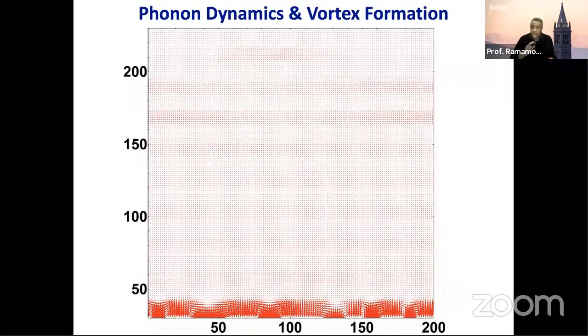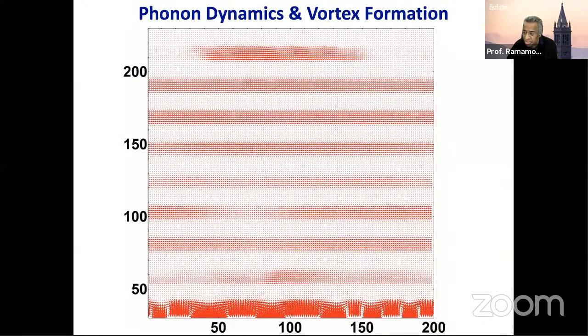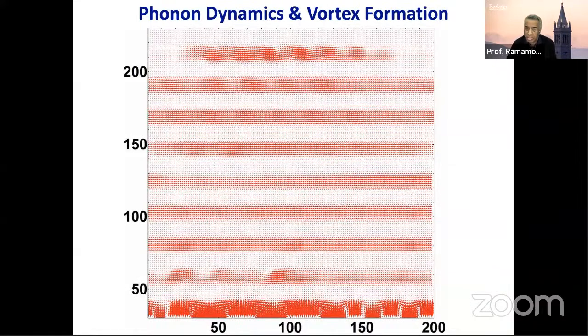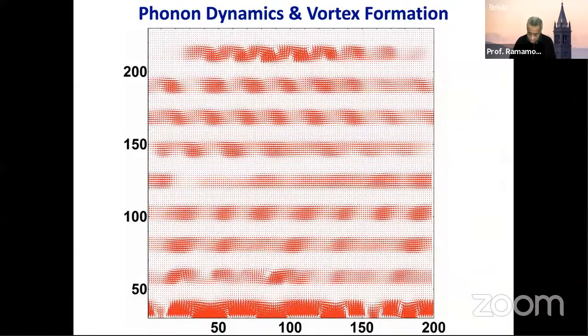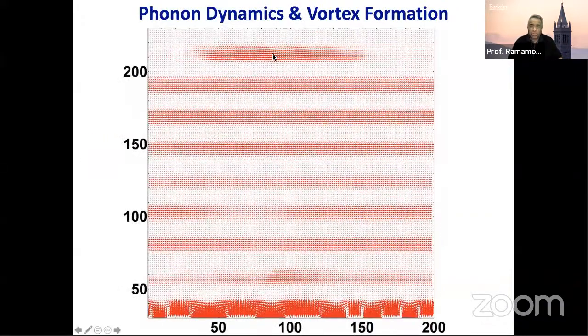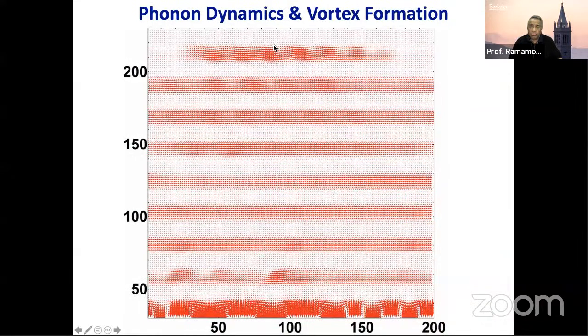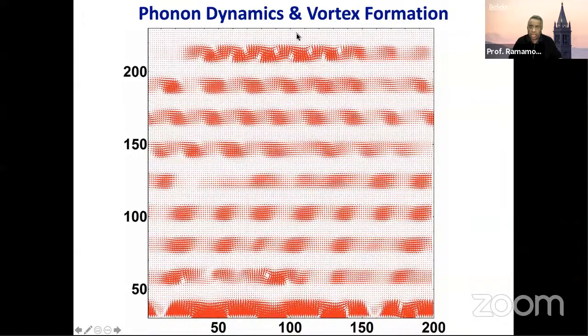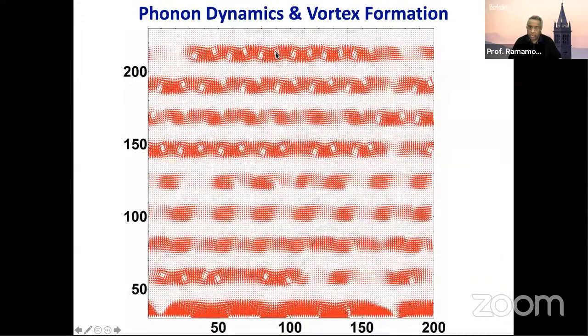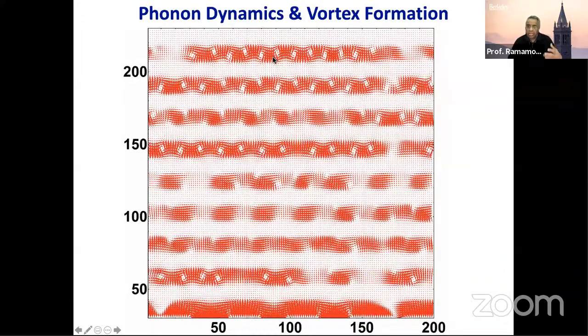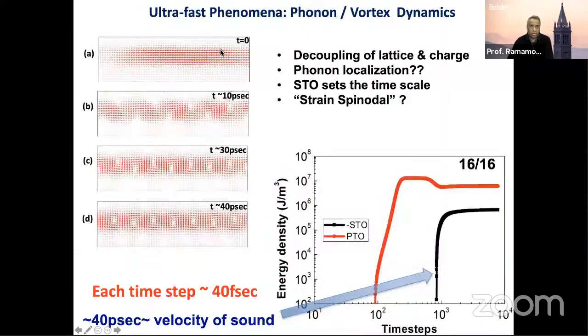So now I'm going to show you the last piece on these vortices, and then we will go to the sister phase. Now, if you look at this picture, what I'm showing you now is time-resolved calculations of how the vortices nucleate. If you pay attention very carefully, you will see that the vortex nucleates at the interface between the strontium titanate on top and the lead titanate here. And it goes all the way from that interface right into here. And you can keep watching this back and forth, but I will summarize it for you. This is time t equals 0. At about 40 picoseconds, that vortex is completely nucleated and gone in.